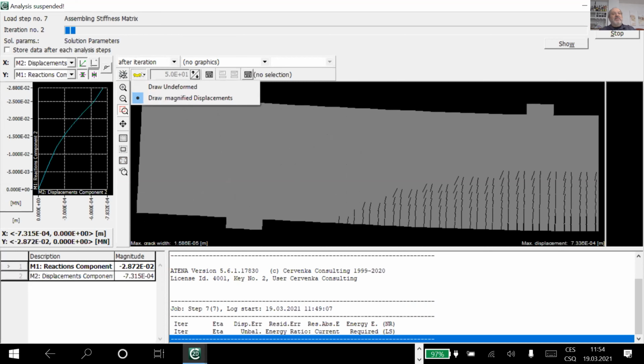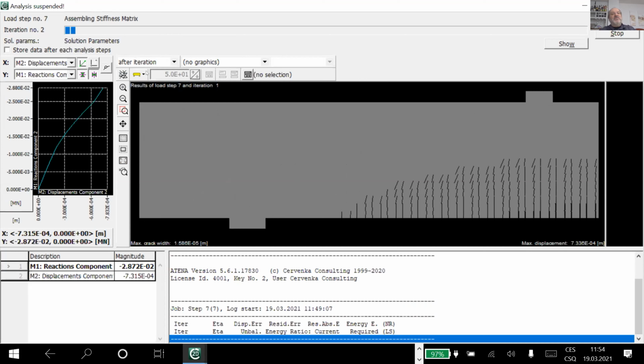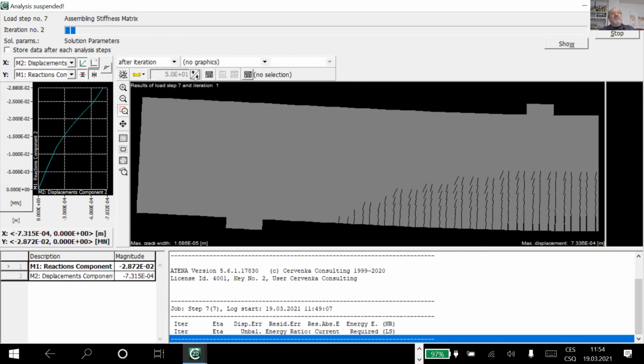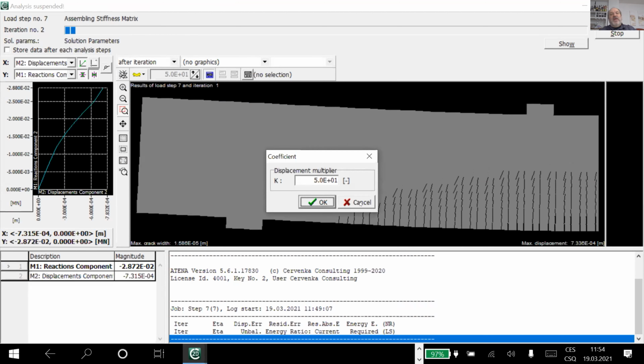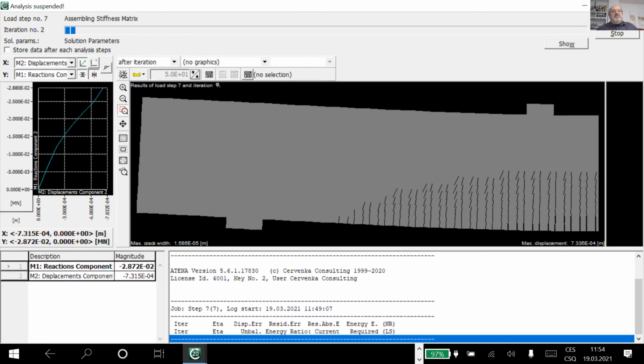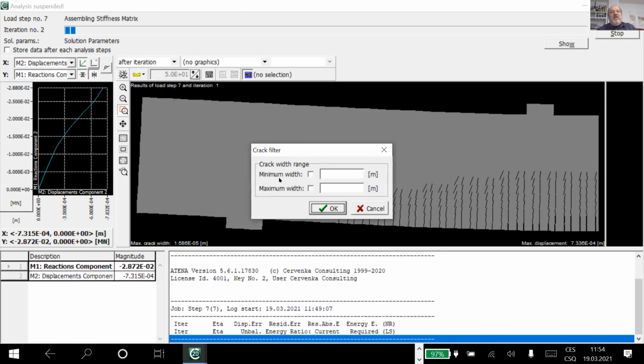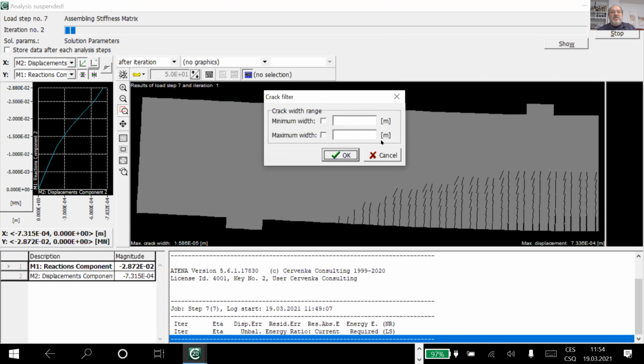We can also scale or not scale the deformation. So it's undeformed or deformed, and the deformation could be increased or minimized, or we can give directly the number. We can also filter the cracks. This is the last option. At the moment, what you see on the screen is the maximum displacement. We are in load step 7, so the maximum is about 0.7 of a millimeter, because we are adding 1/10 of a millimeter per step. And we can see here also the maximum crack width, which is at the moment just 1 multiplied by 10 to the minus 5 or 6 or something like that.